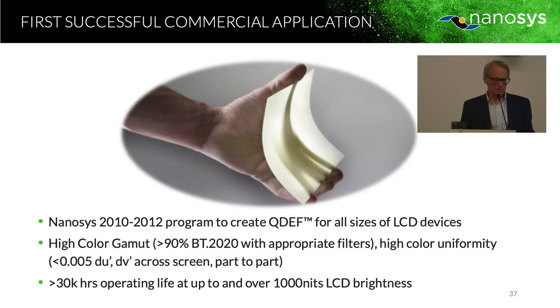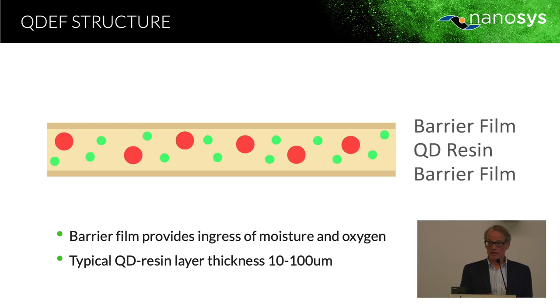What did catch on was quantum dot enhancement film. Basically, this is a film which can be used in edge-lit or backlit displays and has a very long operating life, creates very high brightness, and comes in varieties that are cadmium or cadmium-free today. It's basically a sandwich structure. Red and green quantum dots dissolved in a polymer resin, put between two sheets of barrier film, and then cured. The barrier film prevents ingress of moisture and oxygen, which tends to degrade the properties of the quantum dots over time. The quantum dot layer is maybe between 10 and 100 microns thick, and the whole thing is a few hundred microns in thickness.